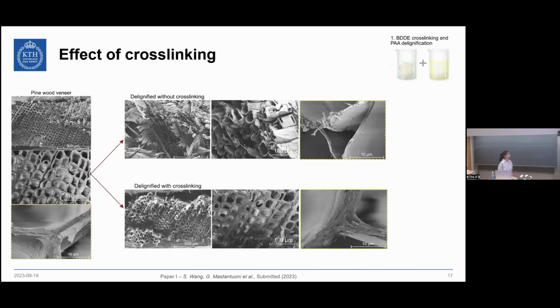Instead, if we first cross-link the material, we achieve a better preservation of the cellular structure. Of course, it does look softer, and this is because we are still removing lignin. But anyway, the cellular structure is preserved, and the middle lamellar region is still maintaining the cohesion between the fibers. These materials were then used in two ways. In the first case, we took the fibers, used a filtration setup with a common paper-making method, and made a film. In the second case, we just used the material that kept its alignment for the densification step.